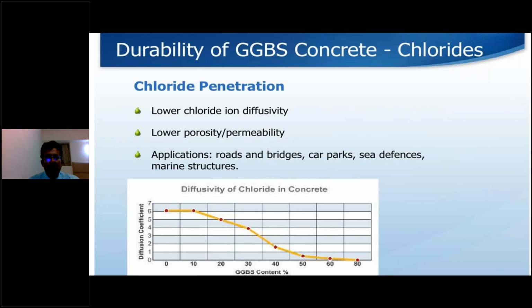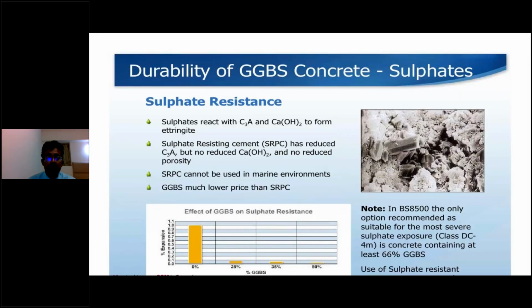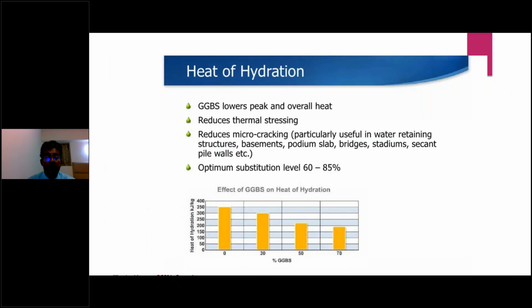So coming to the durability, I've already discussed in length the durability parameters. With higher percentage of GGBS, the chloride penetration coming to almost 0. Similar way, sulfate resistance is getting improved at 50% replacement compared to the OPC mixes. Heat of hydration, especially using more than 60% GGBS. If you are having a raft more than 1.5 meters to 2 meters, it is going to substantially reduce the heat of hydration, which is very good for mass concreting applications.